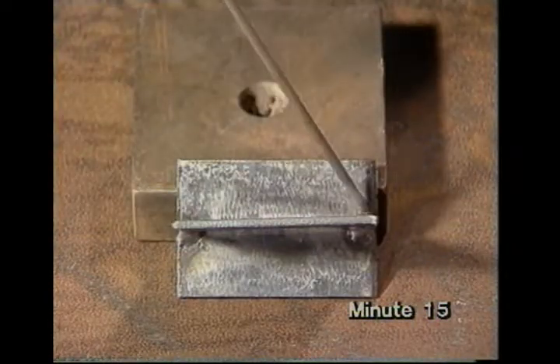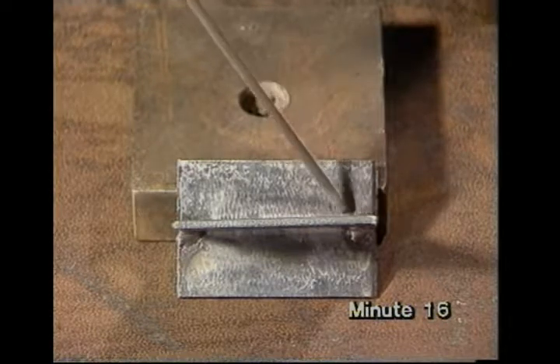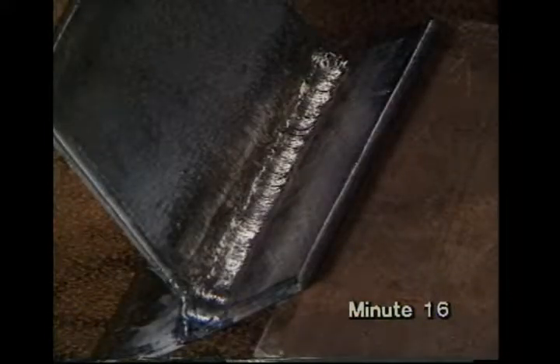Aim the electrode at the usual 70 degrees angle to the line of weld and upright when viewed from the end. This is what the weld should look like after it's been cleaned. To get a better idea of the weld quality, at the Welding Institute we etch a cross-section. This macro section shows that the weld metal has formed a sound metallurgical bond with each part and isn't just sticking to the surface.